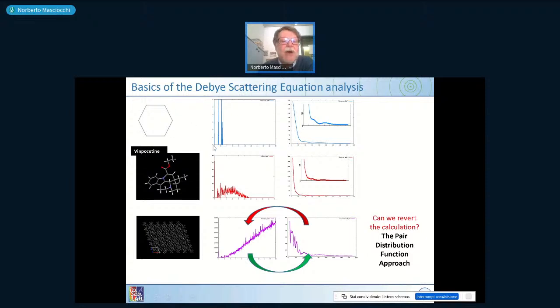This is called the PDF, or the pair distribution function. There are 6 distances at 0 distance. Every atom sees itself at 0 distance. Then every atom sees 2 atoms at a distance of 1 length, of 1 edge of this here. So how many edges do we have here? You have 6 edges. That means that, again, the second peak, which is at the shortest distance, 1.39 angstrom in benzene, has 6 distances all equal.